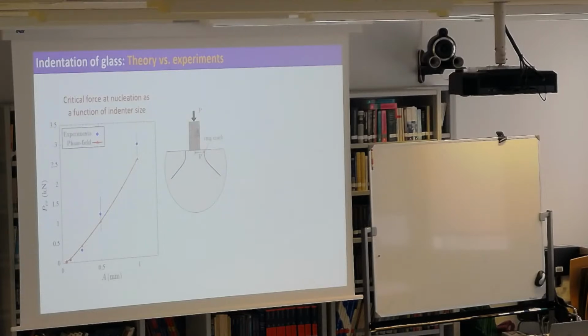The blue is the experiment. This is the phase field. This is interesting if you're interested in buying a car with armor glass, right? This is why glass will not break when somebody shoots at you. This is exactly what happens. This is beautiful. So this is the critical force at which you nucleate the ring crack as a function of the size of the indenter. If the indenter is larger and larger, you have to apply huge force. So to break a piece of glass, that's why you have these little things in the trains, right? You want to hit it with something that has a very small area, and then you only need a small force to break it.